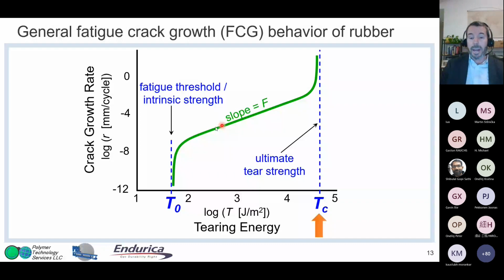Now, if you go even higher in tearing energy, eventually you're going to reach the tear strength of the material, and then you'll just have catastrophic tearing of the rubber. I already mentioned the low end. We'll get to that later, but let's just talk about the tear strength because we can actually use the tear strength to get some information about T0, and we can use both of them together in some cases to learn about the slope of this curve. So let's start with the tear strength, TC.